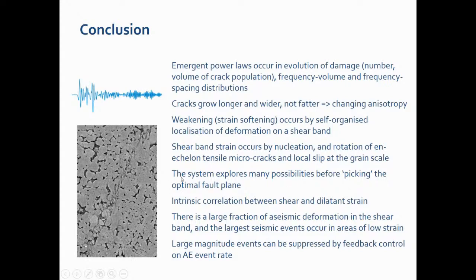The system doesn't know where the fault is going to be right away. It tries out some candidate fault orientations before it picks the optimal one, or the one it's going to be in the end. We see this intrinsic correlation between shear and dilatant strain that you can see on the image. You can see the tensile cracks associated with shear. And then there's a large fraction of aseismic deformation in the shear band. And the largest seismic events tend to occur in areas of low strain out here in the bulk, where it's still brittle. And finally, the large magnitude events can be suppressed by feedback control on the acoustic emission event rate.